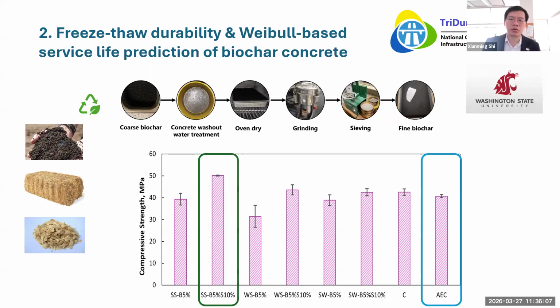The C stands for the group with just concrete without any entrainment, and that strength is slightly reduced when you introduce an entrainment. That's a well-known fact because you introduce a little bit of defect, tiny little micro-sized bubbles. And interestingly, with 5% replacement of cement by biochar and 10% replacement of sand, we actually achieved significantly higher compressive strength at 28 days compared with the entrained concrete. That's a good starting point.